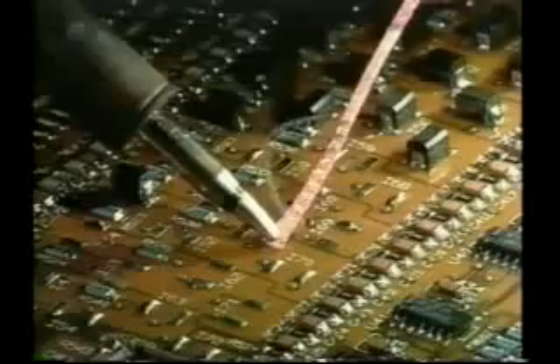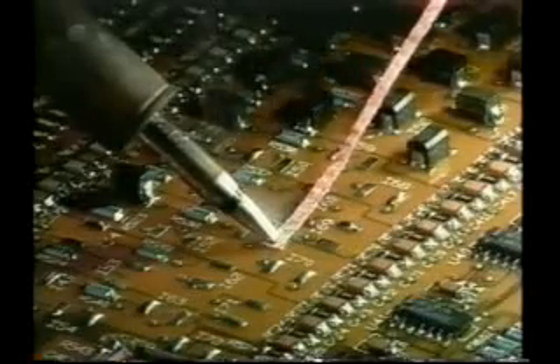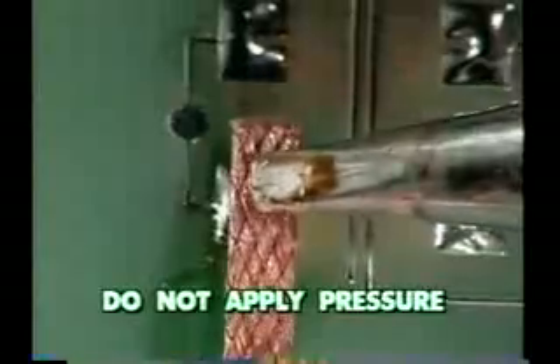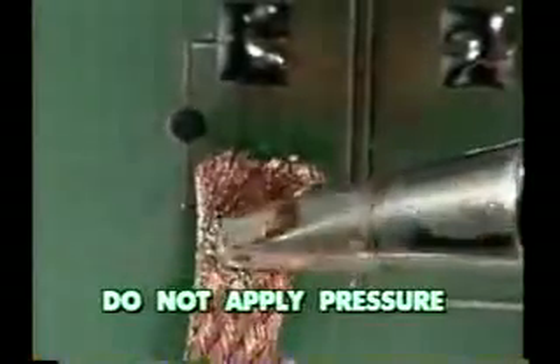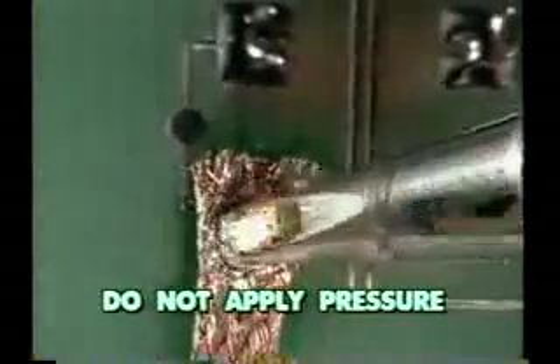As you apply the heat, it's important to avoid putting any downward or sideways pressure on the land. Since the adhesive resin underneath the land is being heated at the same time, the bond between the board and the land will be at its weakest. Sideways pressure can also scrape the land right off the board. Downward pressure can result in a bowed land or an extremely weak bond.